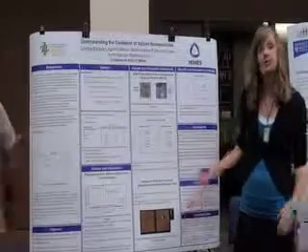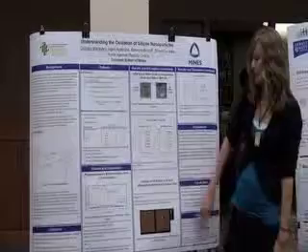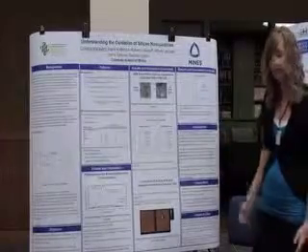The other thing that we saw was that the addition of HF creates much smaller particles that actually have higher quantum yields. And you can see visually in these AFM images that the HF produces much smaller particles, which is advantageous because with the higher quantum yields, you're going to get fewer defects, or that is a sign of fewer defects on the surface.